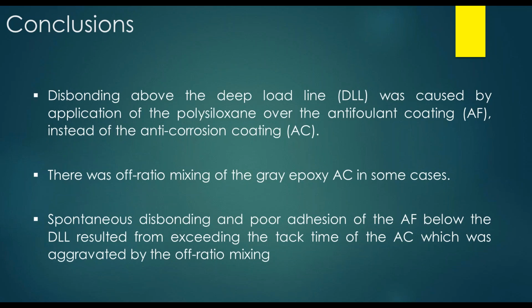So in conclusion, we found that disbonding that occurred above the deep load line was a consequence of application of the polysiloxane over the antifouling coating instead of the anti-corrosion coating. We also found that there was off-ratio mixing of the gray epoxy anti-corrosion coating in some cases. Spontaneous disbonding and poor adhesion of the anti-fouling coating below the DLL was a result of exceeding the tack time of the anti-corrosion coating, which is aggravated by the off-ratio mixing.